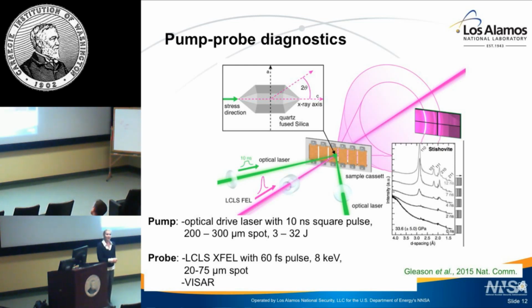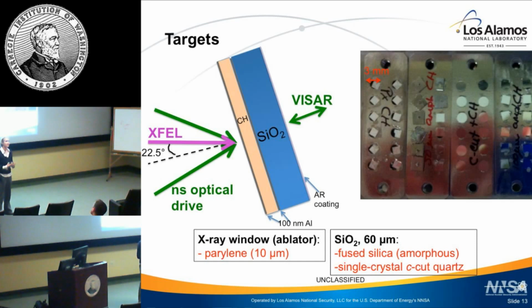Our samples are many. So the rep rate here of our drive laser is once every 7 minutes, okay? So to build up a kinetics data set, to look at time-resolved diffraction, I have to have many, many targets fabricated. So here's an example. This is several millimeter by several millimeter. Hundreds of these targets have to be fabricated in advance for these experiments.